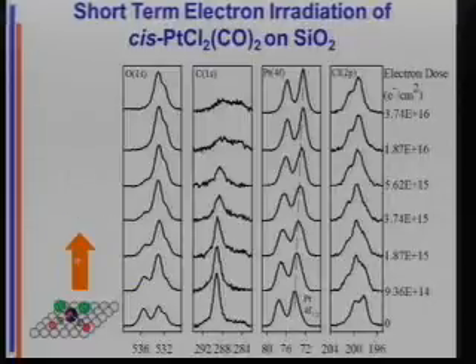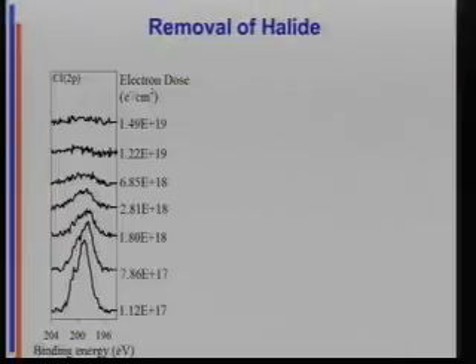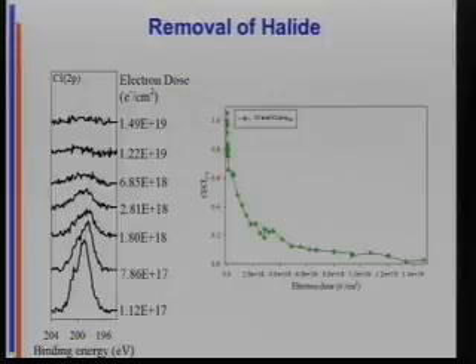And here it is. This is the platinum dichloro-dicarbonyl. Now we're doing it on silica so that we can see the carbon come off as well. This is a better, we learn things, right? Okay. So here's the oxygen going away as we irradiate with electrons. Here's the carbon going away from the carbonyls. And the chloride, well, there it still is for the moment. We're up to the 10 to the 16th electrons per square centimeter. And it's gone by 10 to the 19th. We just got rid of the chloride too. So here's the plot of getting rid of the chloride by electron dose. Okay, there's just a little tiny bit of carbon left.